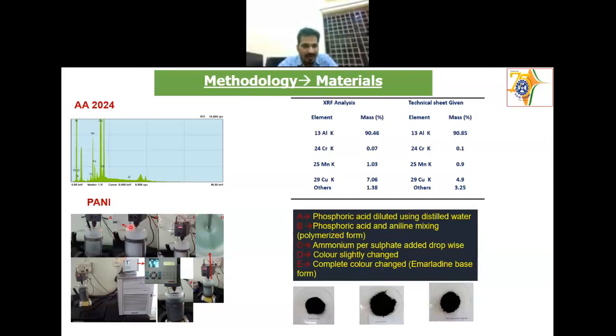So this is the Pani synthesis method. You can see the green color, that means the conducting Pani has been formed. This is the reactor facility available with us. With this, we can make more than 100 grams of Pani in one synthesis itself. Then we'll do all the doping and de-doping. In the de-doped Pani, you can add any type of dopant and dope it again, and make the desired thing.